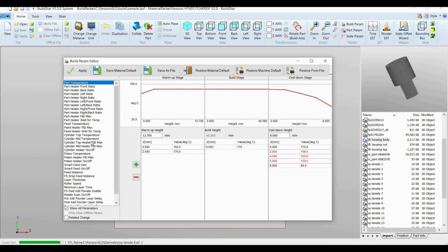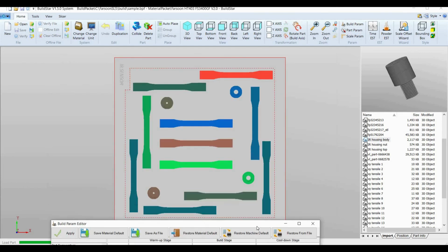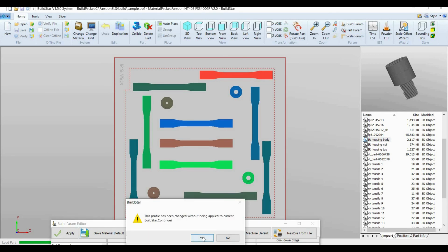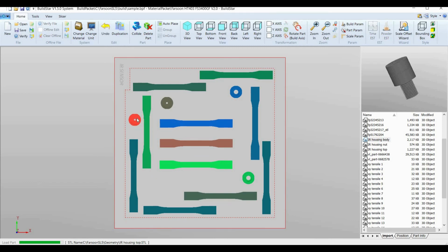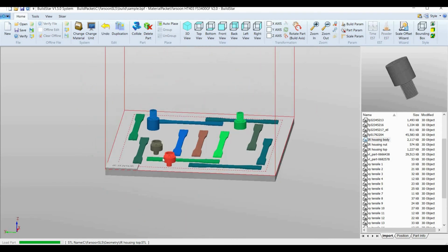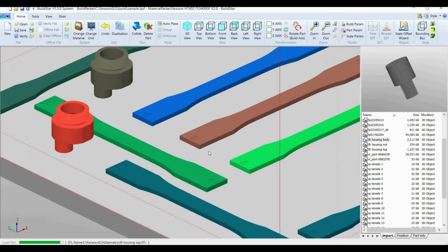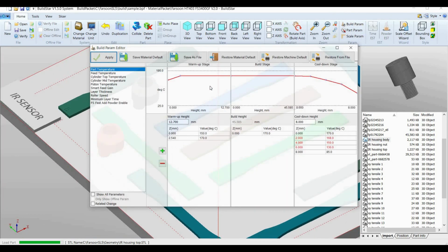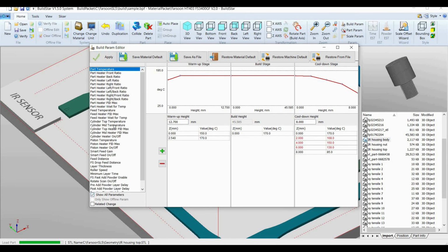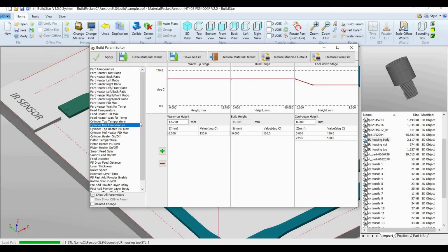Next, we can go down to cylinder heaters. If we see that there are layer lines or banding on parts that are on the outside edges, say if we look at the edges of these tensile bars, or if we had parts on the outside edges and we saw layer lines on these surfaces, then we would go into our build parameters and lower our cylinder top and mid temperatures. Usually 2 to 3 degrees is fine.